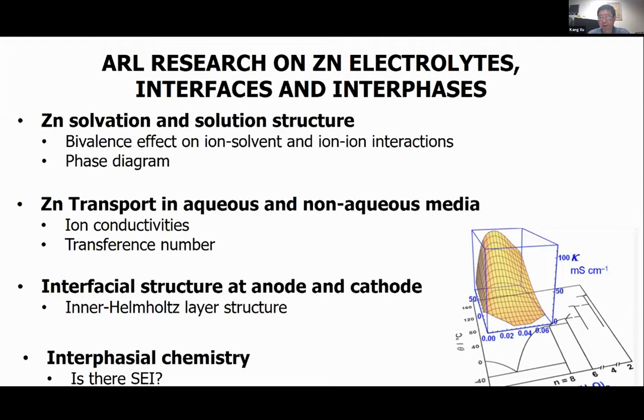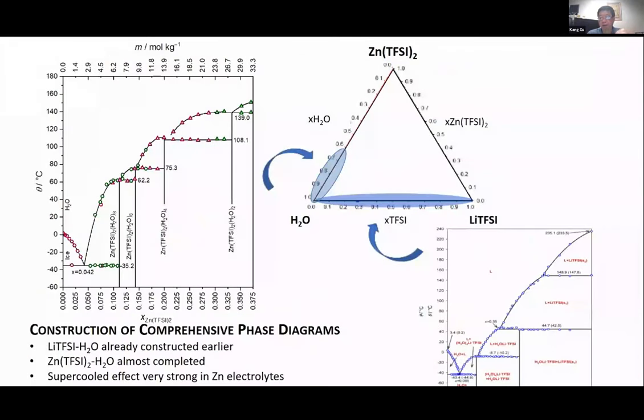Especially we pay close attention to the interfacial structure at both anode and cathode, because we realize that the structure of the inner Helmholtz plane plays a key role in either promoting or suppressing the charge transfer at those interfaces. And the final question we need to answer is, is there an SEI? Because the traditional wisdom is that the SEI cannot work for multivalent cations. The most prominent example is magnesium. Once you form an SEI there, magnesium ion cannot pass through. And we want to study this case because we want to stabilize the anode surface, so we have to leverage the SEI. So as a fundamental part of this work, we first constructed the zinc TFSI and water phase diagram.